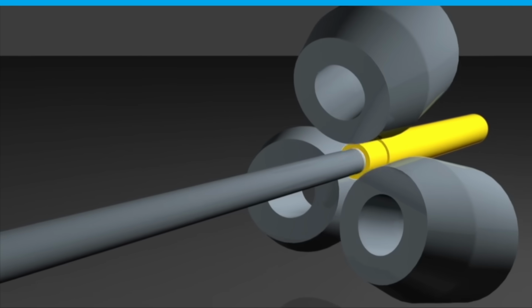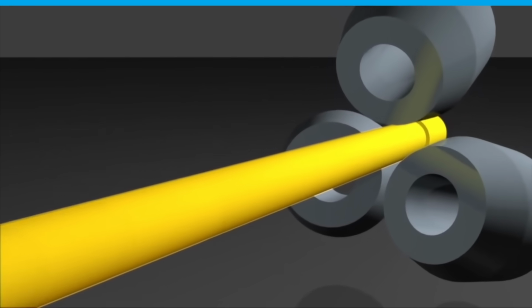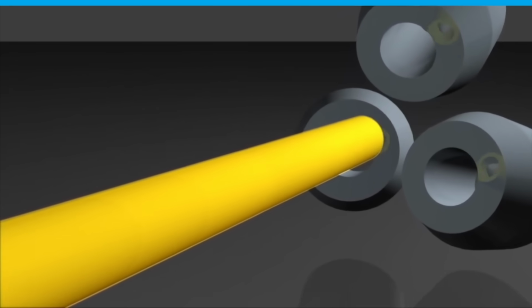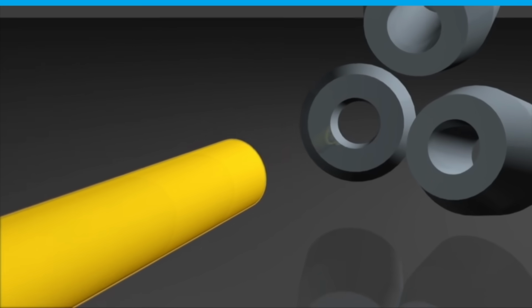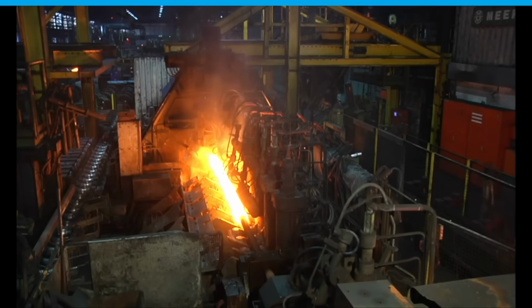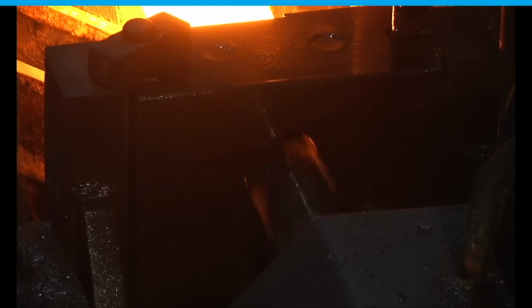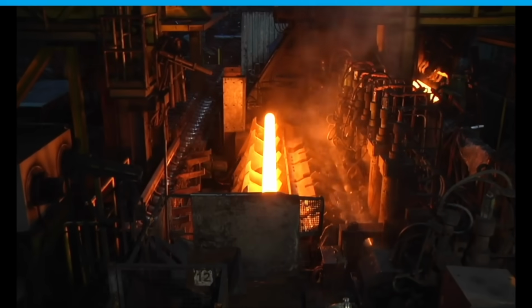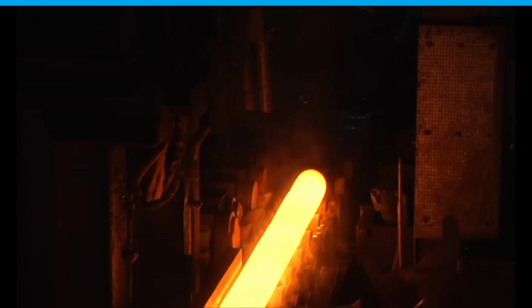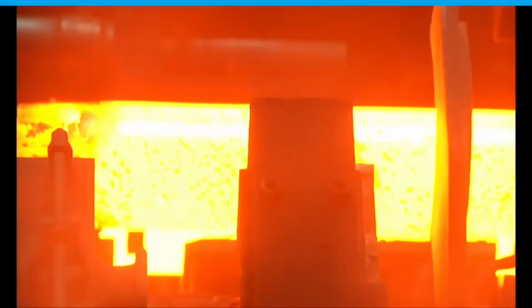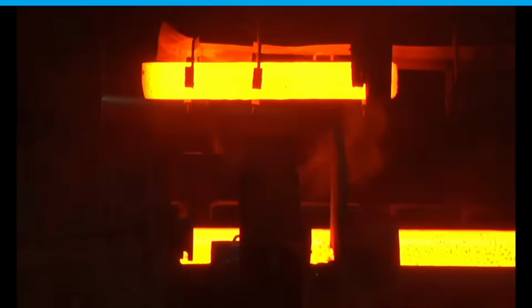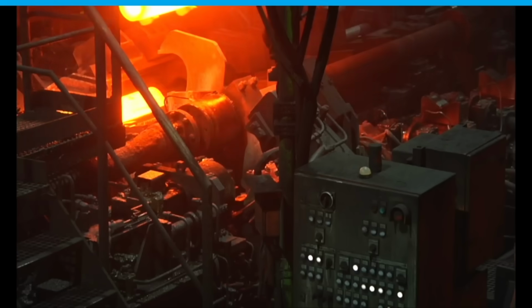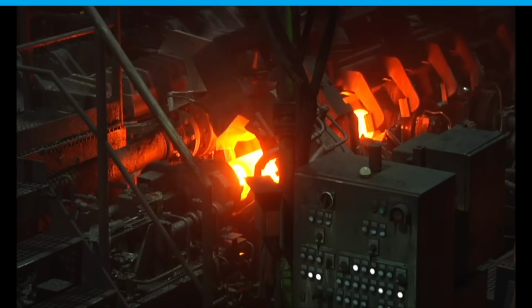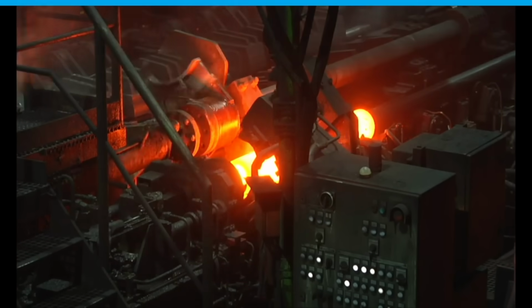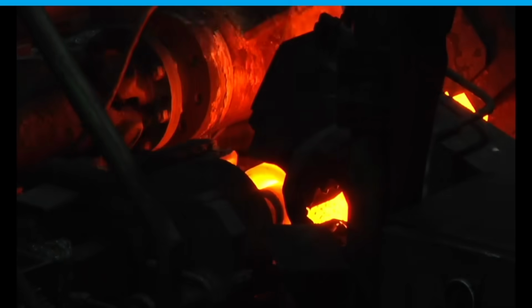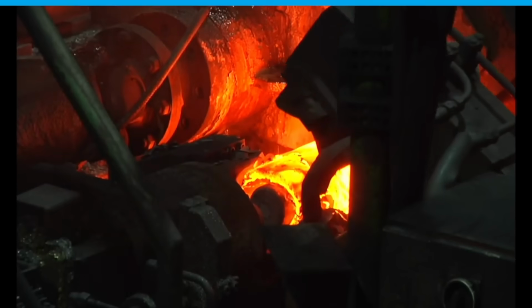This inclination makes the billet move over the mandrel and roll out, creating a hollow shell while ensuring a uniform wall thickness. This cross-roll piercing and elongation technique allows for superior material properties and precise dimensional control. After cross-rolling, the mandrel bar is pulled out of the hollow block. Then a transport system consisting of transfer rollers, roller tables and manipulators transports the rolled material to the main forming unit of the pipe.